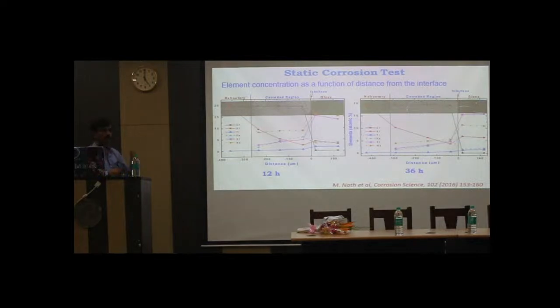Now, why is that so? The corrosion rate ceases after 12 hours. We try to analyze in detail. So we have taken a small sample from the interface, keeping on one side the glass and on the other side a small amount of refractory, keeping the corroded region fixed, and then we measured the elemental concentration by point analysis. Now we plotted the point analysis with this refractory. It contains aluminium, Cr2O3, and this side is the refractory.